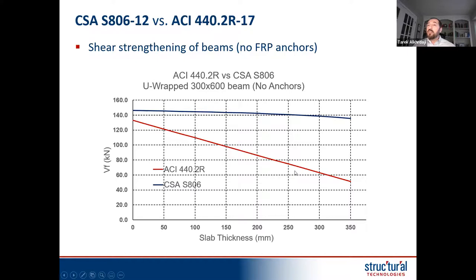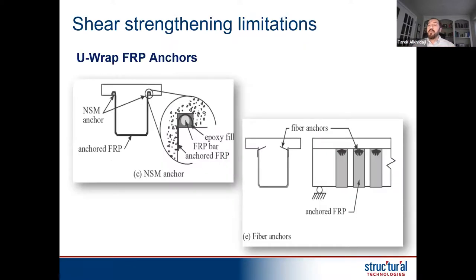If you don't pay attention to that and you don't use that when you use the CSA, the capacity would not drop as much, and you can be twice as much as your true contribution from the FRP. This is only the FRP contribution I'm adding in here. So I just wanted to make sure visually it's clear to everyone why it's important not to include the slab depth.